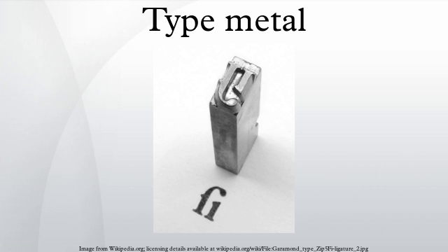Historic references to type metals. Joseph Moxon, in his Mechanick Exercises, mentions a mix of equal amounts of antimony and iron nails. The antimony here was in fact stibnite, antimony sulfide. The iron was burned away in this process, reducing the antimony and at the same time removing the unwanted sulfur. In this way ferrous sulfide was formed, that would evaporate with all the fumes. The mixture of stibnite and nails was heated red hot in an open-air furnace, until all is molten and finished.